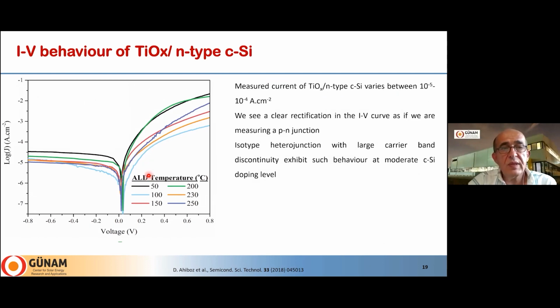Here we see standard rectifying junction type results. We have high current for the positive voltages and less variation for the negative voltages. So it means that electrons can flow very easily from silicon into titanium dioxide, but the charge carriers are blocked or less mobile for the negative voltages. This proves that the titanium oxide layer is an electron selective layer on N-type silicon.